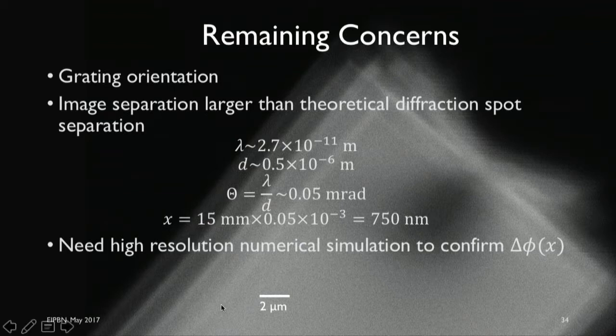But if you look at the image, you can see that the separation between these images, or reflected images, is almost twice that amount, or a little bit more than twice that amount, which at this point we can't fully explain. And ultimately, we need a high-resolution numerical simulation to confirm the amount of phase shift that we're getting. So we need to actually make sure that with the current setup, with the current electric field, and with the current diffraction gratings that we have, we can produce enough phase shift that could cause diffraction. That's still underway, and we're working on that as well.